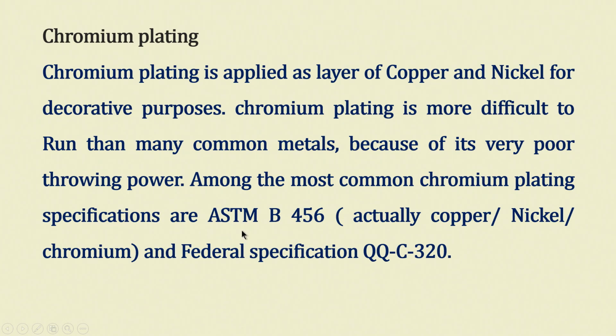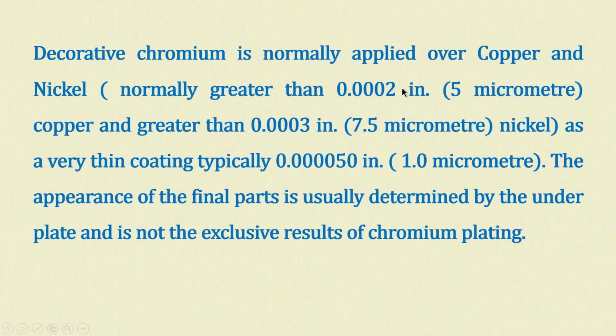Among the most common chromium plating specifications, we have ASTM B 456 that corresponds to copper, nickel and chromium, and a federal specification also is there. There are several other Indian standards as well. So, decorative chromium, again just imagine your knife or scissors, which looks very shiny. They all look like stainless steel, what we use in our normal kitchen, but decorative chromium is normally applied over copper and nickel, normally greater than 0.0002 inches, that is approximately 5 microns, and copper has to be greater than 5 microns copper and greater than 7.5 microns nickel, with a very thin chromium coating of about 1 micrometer.